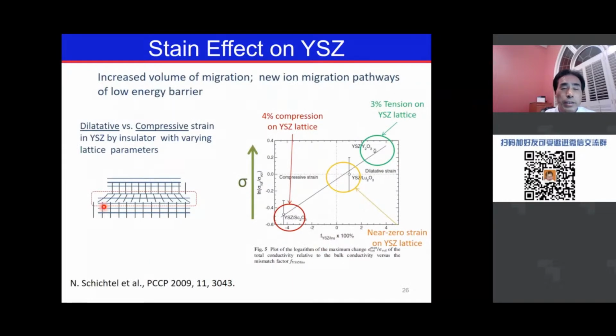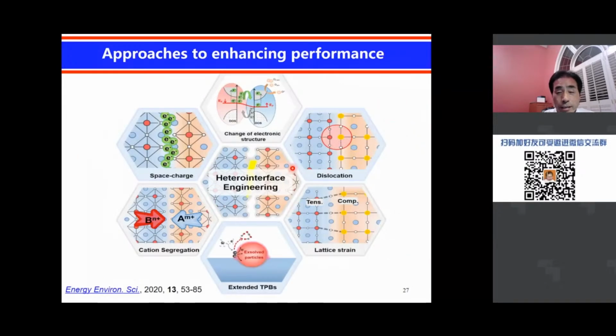So as an example here, this is strain created on YSZ, for instance, yttrium-stabilized zirconia. If you grow a thin layer of YSZ on different substrates, you can create either compressive strain or tension. Yeah? And as you change the nature of the strain, the ionic conductivity can change quite significantly. This has been demonstrated: you can change the conductivity by an order of magnitude. So that uses the lattice strain created at this interface.